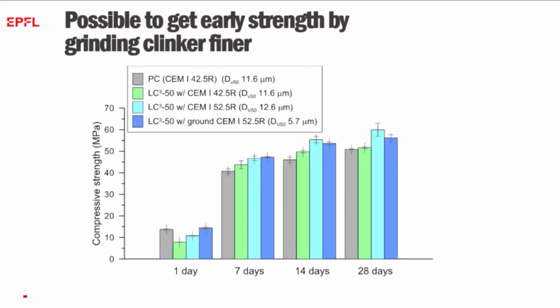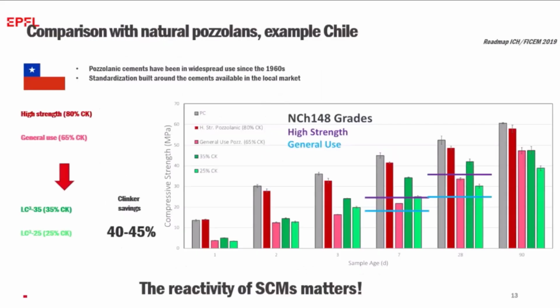And of course, one of the main limitations is the strength development at early age. If you're producing these materials in a cement plant, you can optimize the particle size distribution of the clinker component, and you can get even the same strength at 1 day. And this doesn't negatively impact rheology. You have some impact of the calcined clay, which can be dealt with superplasticizers, but the grinding of the clinker doesn't make it any more difficult.